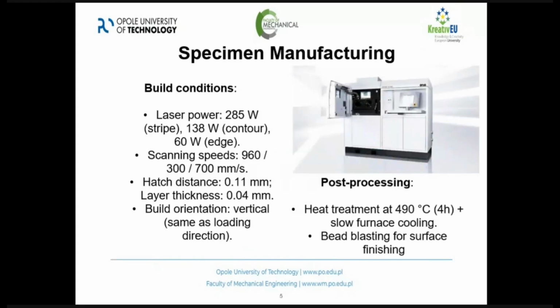So this is the system and the building condition, the laser power, the scanning speeds, hatches, and all the other important stuff. After the printing, the specimens were heat treated at 490 degrees for 4 hours with slow furnace cooling. This is according to the EOS data sheet, right?